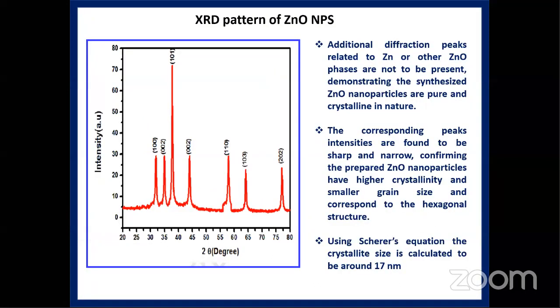This is the XRD pattern of the zinc oxide material. You can see the well-known peaks confirm that the material has a crystalline nature, indexed by JCPDS, Joint Committee on Powder Diffraction Standards. So it is very good. These planes correspond to the hexagonal structure of this zinc oxide nanoparticle. Using the Scherrer equation, we can calculate the crystallite size. It is found to be 17 nanometers.